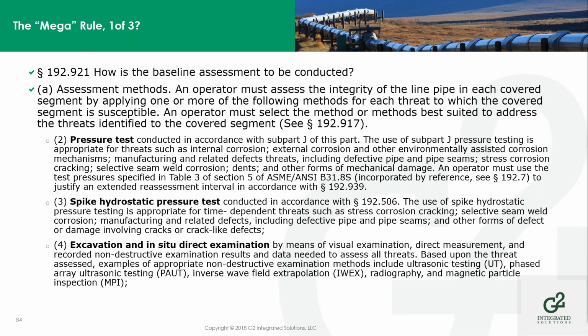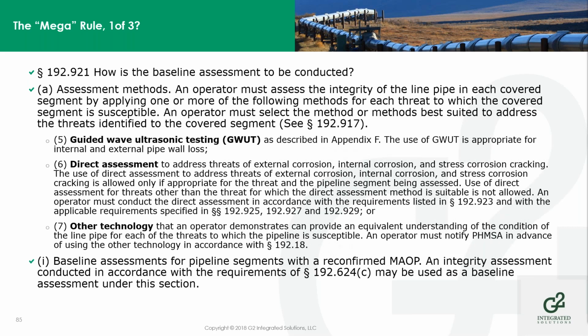Pressure tests: you select the method or methods best suited to address the threats. A pressure test may be the best method to assess the threat. A spike hydrostatic pressure test, excavation, and in situ direct examination are methods to do the baseline assessment, as well as using guided wave, using direct assessments, or any other technology. Again, once notified to PHMSA. Baseline assessments for the segments with a reconfirmed MAOP, integrity assessments conducted in accordance with the requirements of 624, can be used as that baseline assessment if you follow that path.